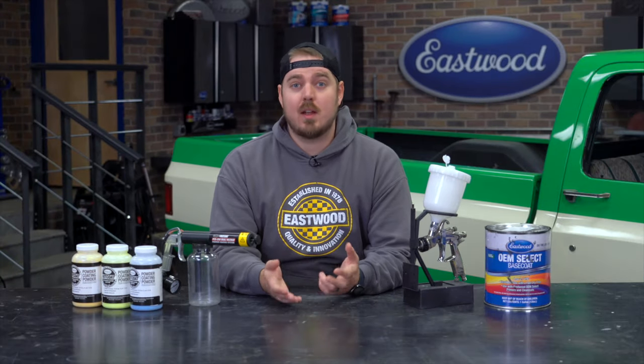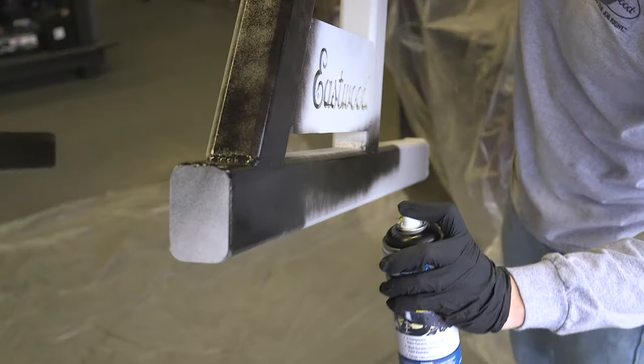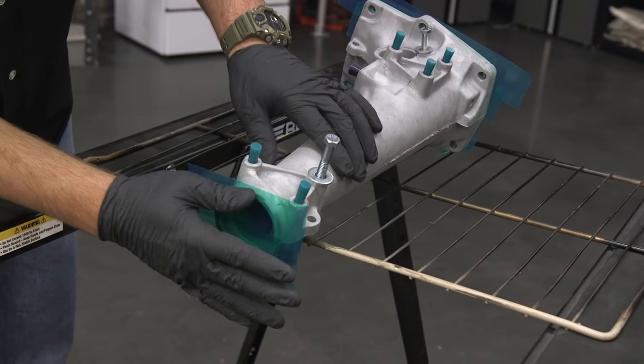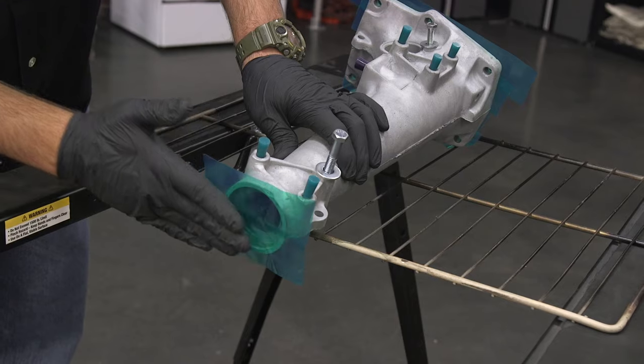There are some downsides to powder coating. Number one is the thickness of the coating — you will not be able to get as thin as traditional paint, so any parts with close tolerances will be better off being painted. If you want to keep powder out of certain areas, you can use high-temp silicone plugs or high-temp tape to keep it out of the areas you don't want it.